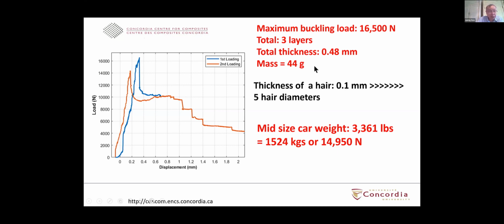The load we obtain is about 16,500 Newton. And you wonder how much is that 16,500 Newton? Take a look at the weight of a car. The weight of a car is around 3,361 pounds, or 14,950 Newton. So basically, this cone with a mass of 44 grams and a thickness of 0.48 mm, less than 5 hair diameters, can support more than the weight of a car. So that is the case.